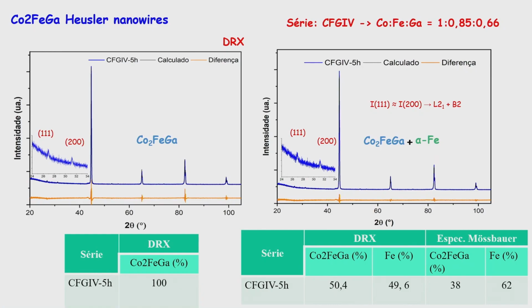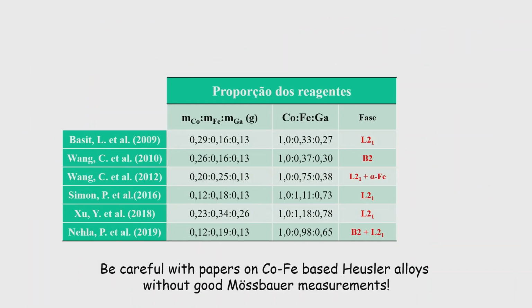Because if you use only X-rays, you cannot distinguish. This is a fit using the same spectrum, the same diffractogram, using only cobalt-2 iron gallium, and having 50% of iron-57, you see? It's more or less the same. That means if you don't do Mossbauer, be careful. The message is: be careful if you see works on Heusler alloys without good Mossbauer spectroscopy.